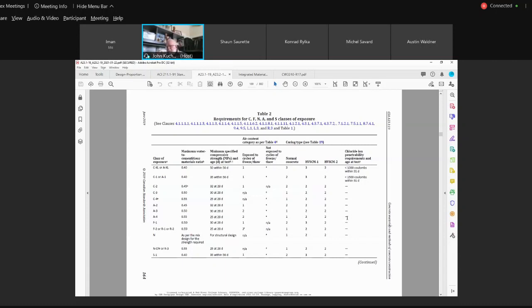And that bubble spacing has to meet CSA criteria. Even though you might meet 5 to 8%, let's say you got 6% air, but the spacing factor is out to lunch, that mix won't be approved. Because it's the spacing factor between bubbles that is more important in relationship also. I mean, don't get me wrong, you still need that range of 5 to 8, but just because you have it, it may not mean you got the spacing factor. And that is a function of your materials, especially your sand, your admixtures, and very particularly, your air entraining admixture.